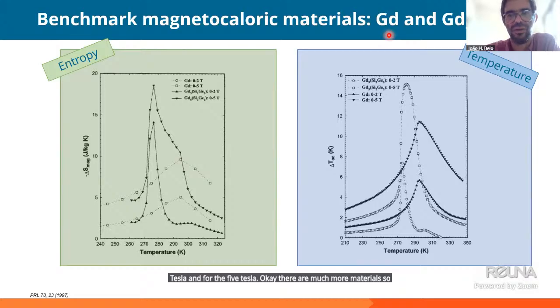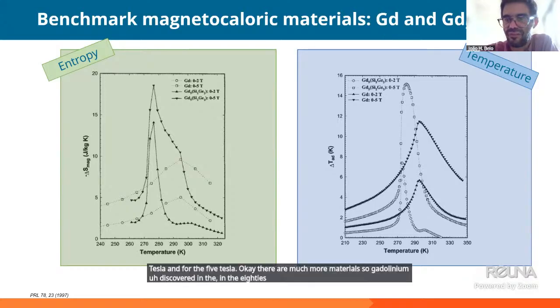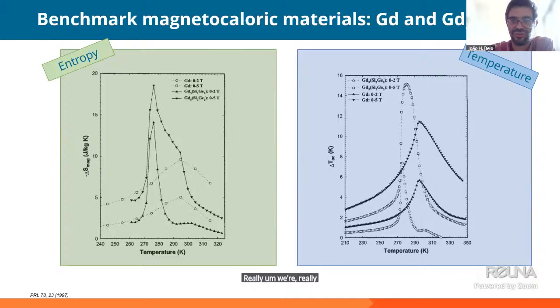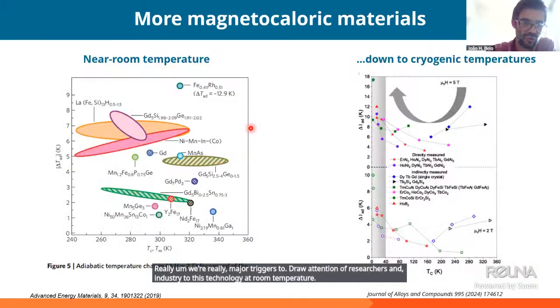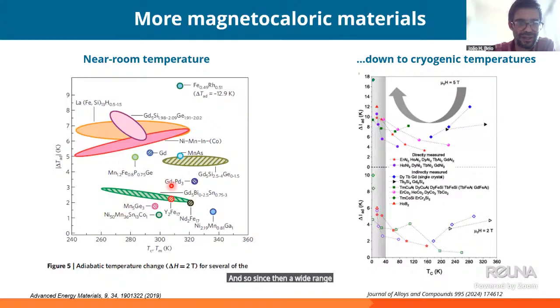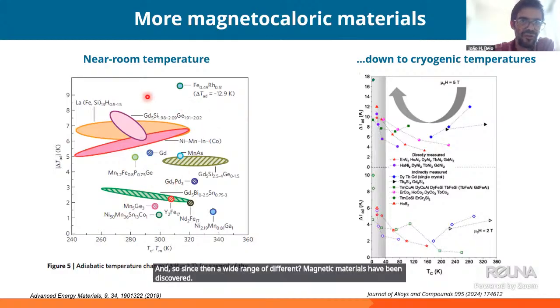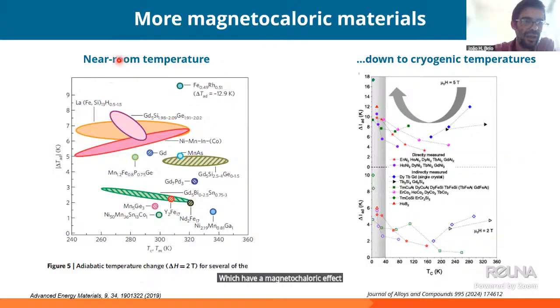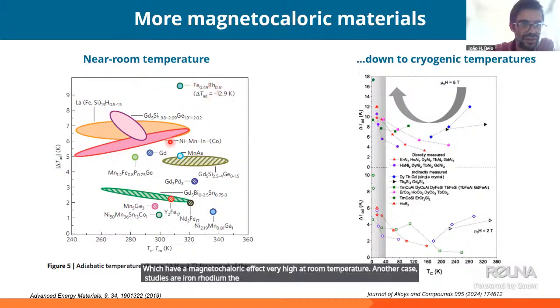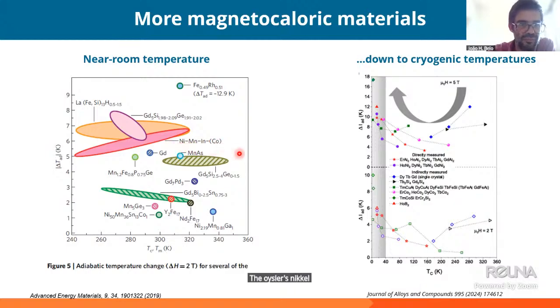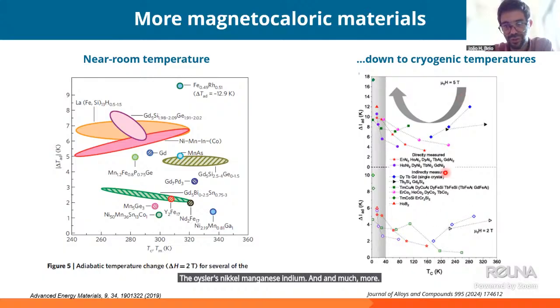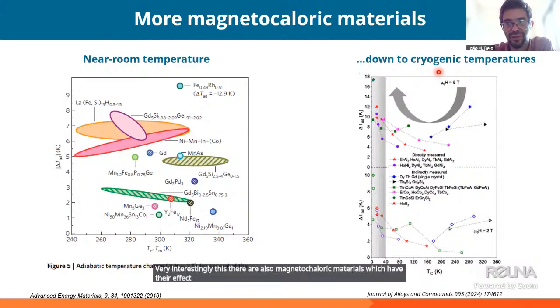So gadolinium discovered in the 80s, and then the 522 discovered in 97 really were major triggers to draw attention of researchers and industry to this technology at room temperature. And so since then, a wide range of different magnetic materials have been discovered, which have a very high magnetocaloric effect at room temperature. Other case studies are iron rhodium, the lanthanum iron silicon, the Heusler nickel manganese indium, and much more. Very interestingly, there are also magnetocaloric materials which have their effect maximized at cryogenic temperatures.